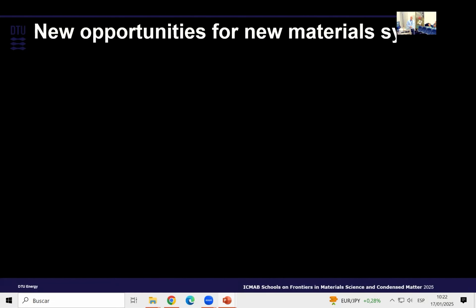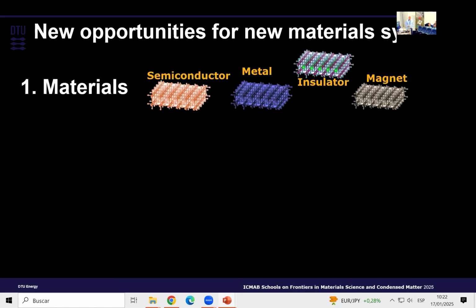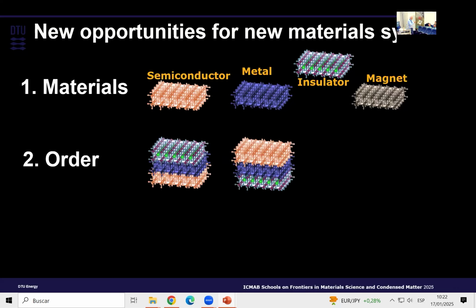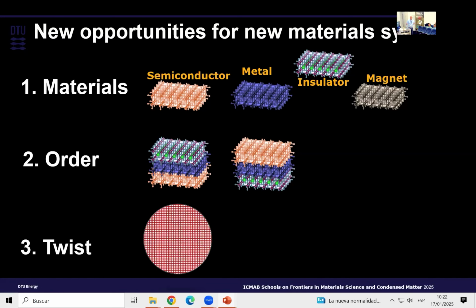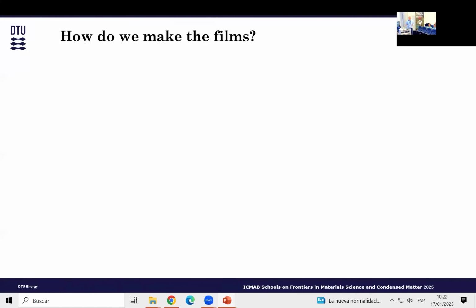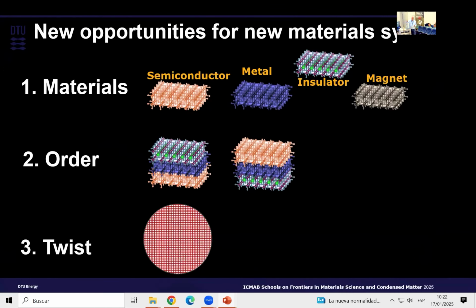So this brings about a new opportunity for a new material system. Why? Because we have materials which are correlated, and therefore there are a lot of properties. Some of them are semiconductors, metals, insulators or magnets. We can also order them differently, and here is where the order plays a role. And on top of this, there's a video there, and you can twist them also. So there are 3 degrees of freedom where you can play with the material, and you can see that there is an infinite amount of possibility. You can take different materials, order them differently, twist them differently, and play again. The playground is really rich in possibilities.